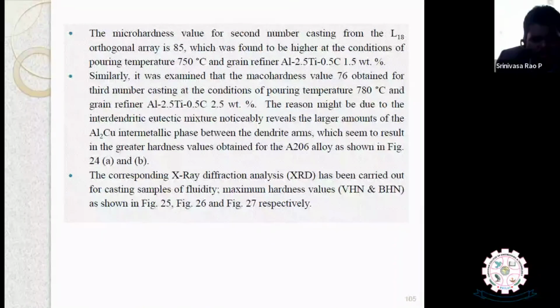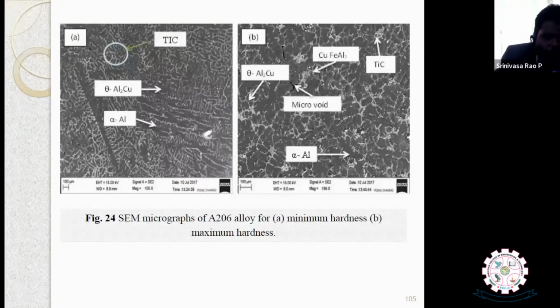What might be the reason? The interdendritic eutectic mixture noticeably reveals larger amounts of the aluminum-copper intermetallic phase between the dendrite arms, which seems to result in the greater hardness values obtained for the A206 alloy, as shown in the figures. Okay. And we have carried out XRD analysis also.